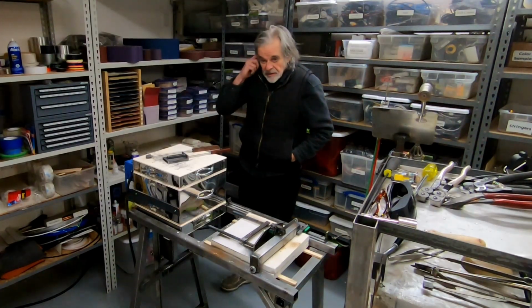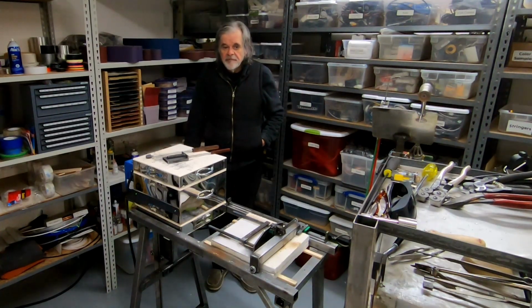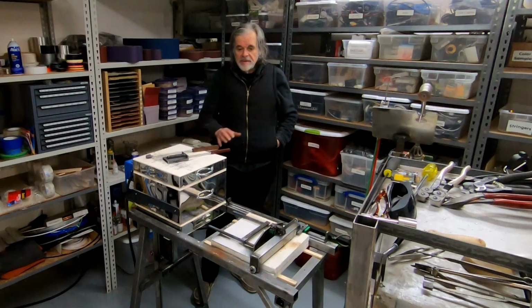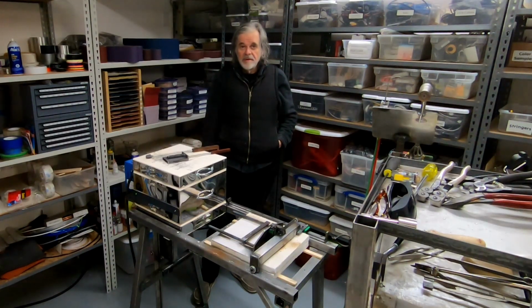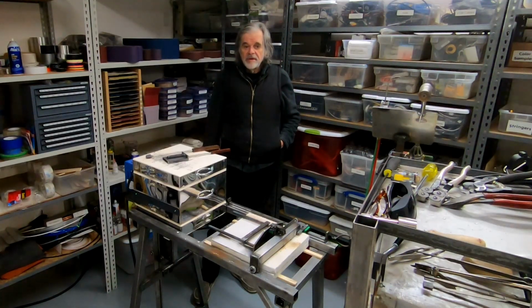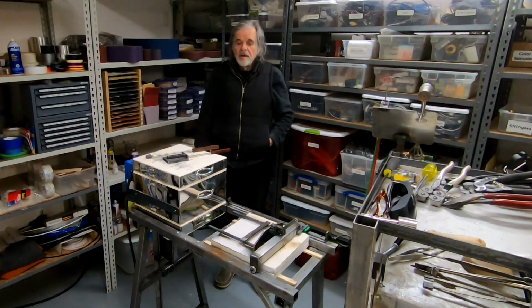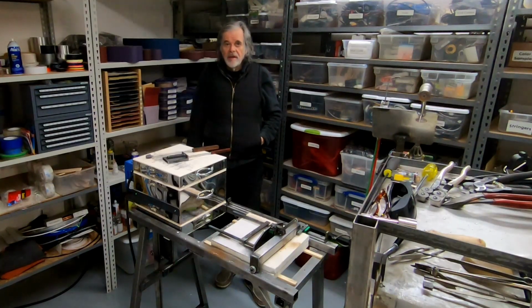And so what I've learned with the experience that I'm developing while doing this is that if I have the piece that has been sitting out in the cold air for a while, and yes, it is pretty cold out here in the Northern California winter in December, when I take the piece out, the plate is rapidly losing heat. And so even though I'm putting the piece into a 1700 degree kiln, it still takes a while for everything to come up to heat. And of course, the top surface of the glass, the part that I'm trying to work on, is the part that gets hot faster, and the critical area where the glass meets the ceramic takes the longest time to heat because the ceramic is heating from the bottom up, the glass is heating from the top down.